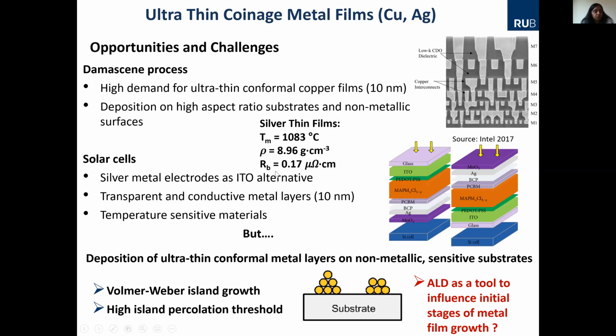Silver is a good choice. It is expensive. On the other hand, it has a good high melting point. It has a low resistivity, and also actually you can grow them, but still this issue will come in terms of percolation and higher thickness. So for solar cells, for example, you need transparent, conductive materials, and one possibility is to replace this ITO with silver. Same stack of material system, but instead of ITO, you could take silver.